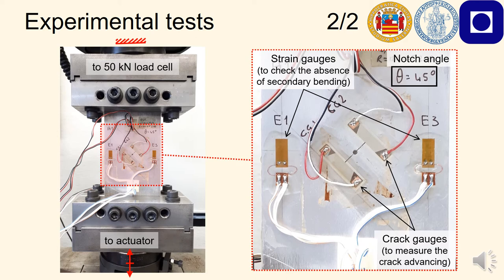For all specimens, we used crack gauges glued on the notch tips to measure the crack advancing in the first part of crack growth. After this initial part of propagation, when the cracks propagated sufficiently, we stopped the tests every some thousand cycles and we took photographs to measure the crack length. Doing this up to failure allowed us to monitor the whole crack growth.